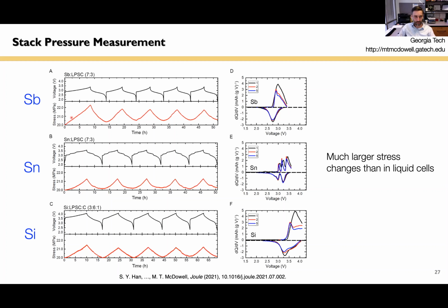And so it turns out by investigating the details of how the stack pressure changes, we can learn some things about these composite electrodes. One of the big conclusions, though, is that there are much larger stress changes in these cell stacks than what you find in liquid cell batteries. Similar measurements have been done in conventional liquid cell batteries with alloys and with lithium. And you see, depending on the cell configuration, which is important for this, hundreds of kilopascal changes, whereas here we're seeing multi-megapascal changes.